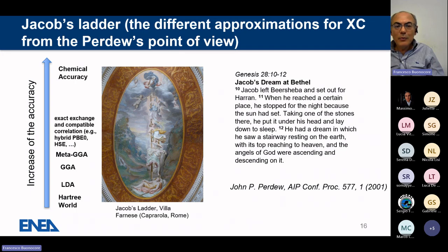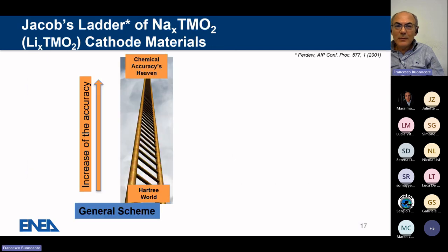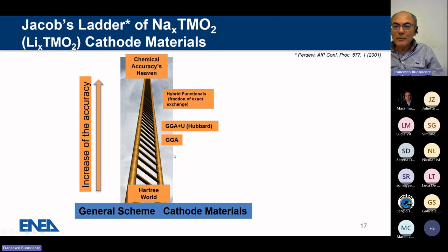And a very good approximation is the one with the hybrid functional, where you calculate from the orbitals the exact exchange, and you include a fraction of the correlations. But this approach is very expensive. And then you have the computational chemistry approaches that are very expensive and not very suitable for condensed matter. For cathode materials, we adopt the following approach. We adopt the generalized gradient approximation, that is not quite satisfactory.